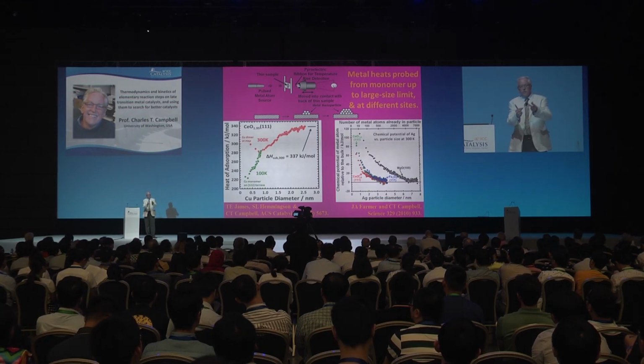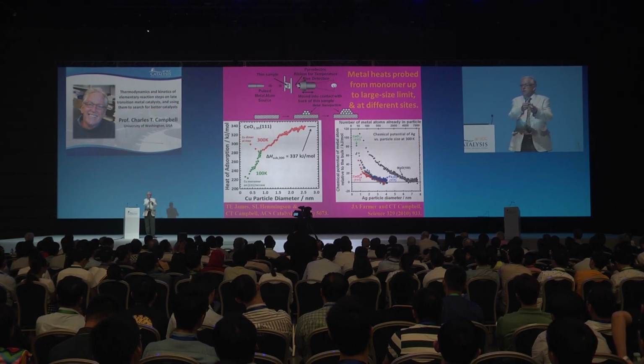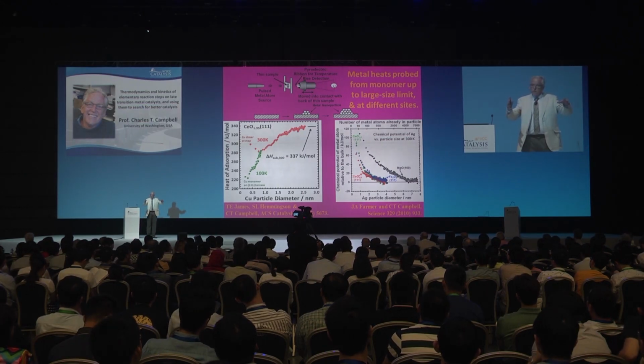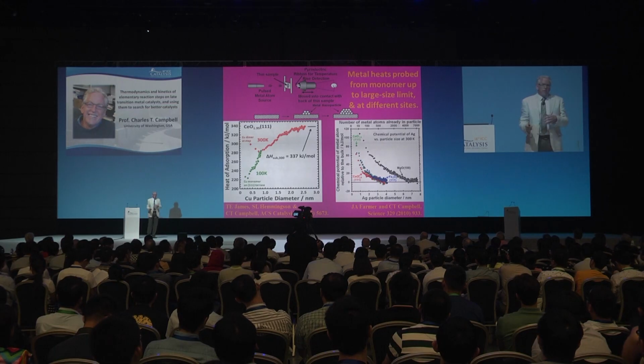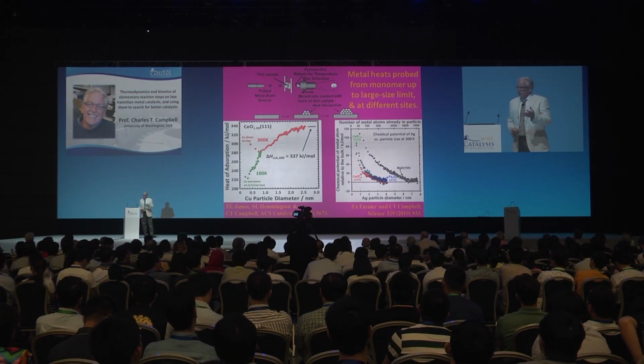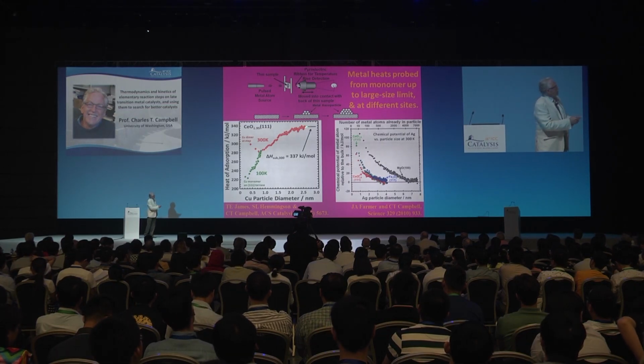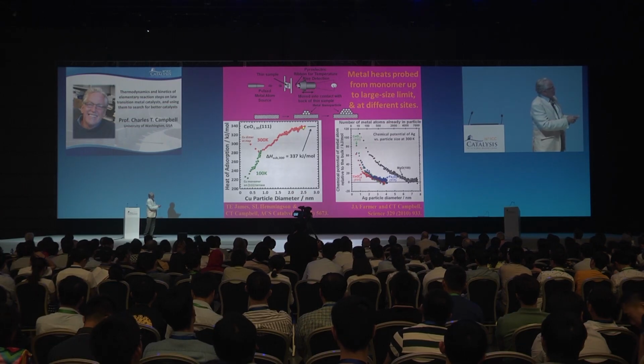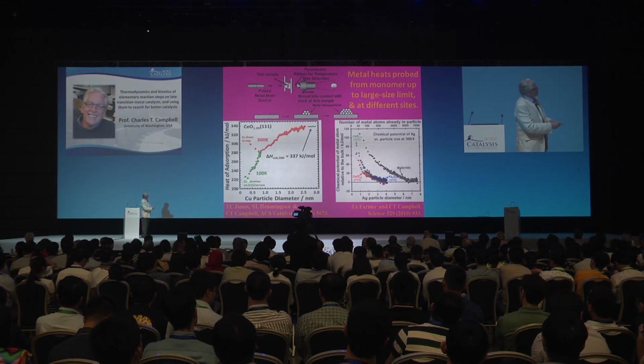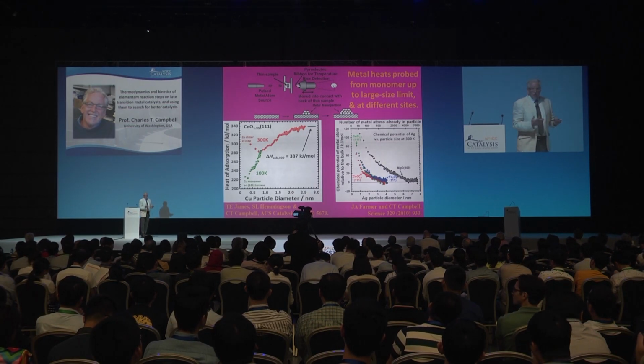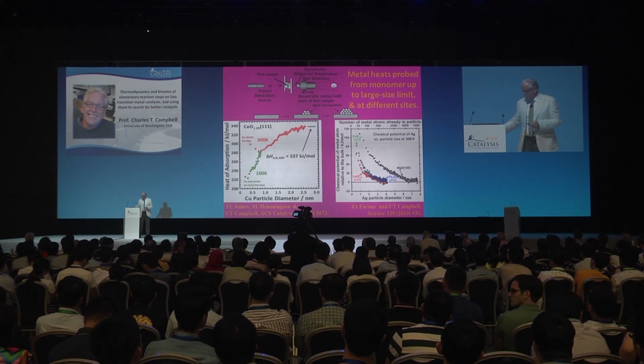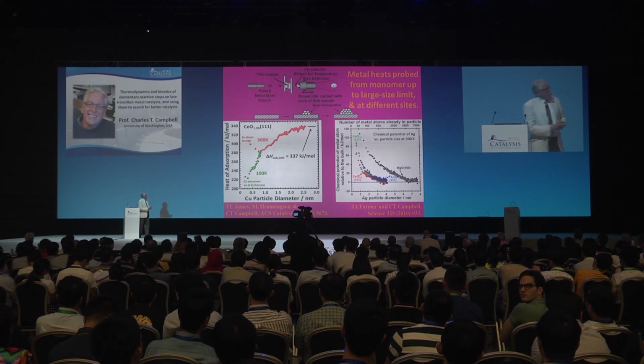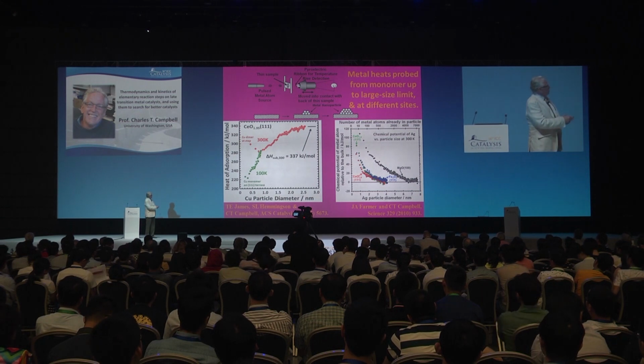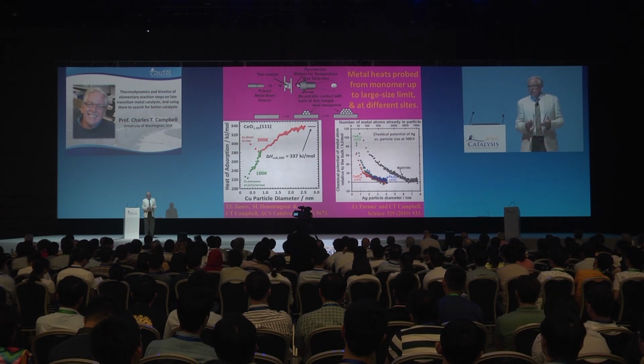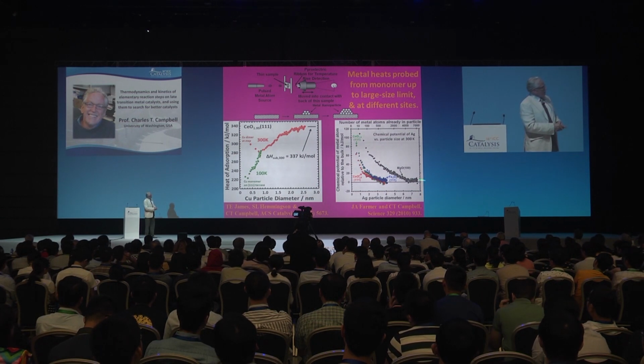When you have a trimer, you can make 3 bonds. By the time you get to a large particle, on average, you make 6 metal-metal bonds when you add a metal atom to a particle in the large size limit. So this is basically like making 6 metal-metal bonds. You can see it drops down by a huge amount, largely because you're making fewer metal-metal bonds in the adsorption energy.